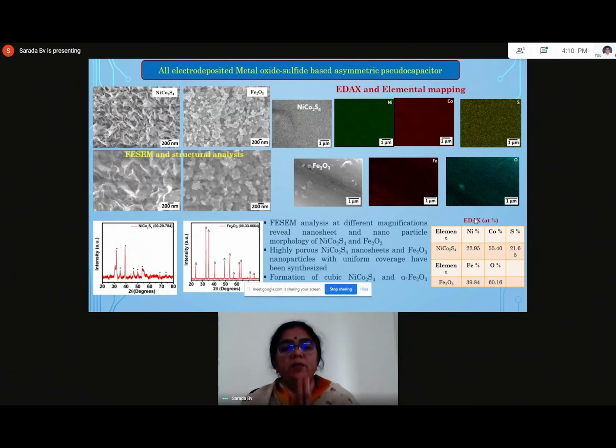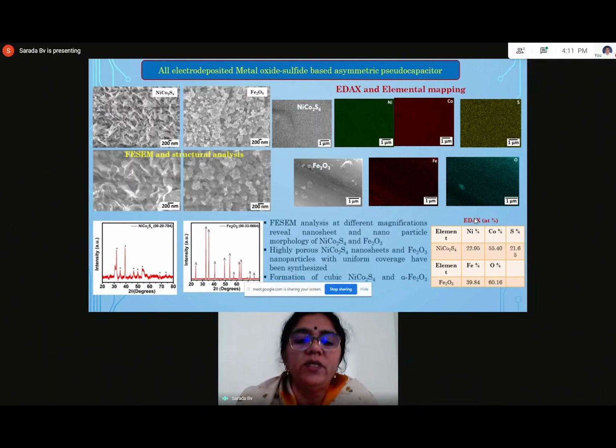And finally, previously what we have used is one carbon electrode and one metal oxide electrode and prepared an asymmetric capacitor. And now here, a step further she has gone and prepared an all-metal-based pseudocapacitor, both metal oxide or metal sulfide, metal composite based, by using nickel cobalt sulfide as one electrode and iron oxide as the other electrode in order to further improve the performance of this asymmetric pseudocapacitor. And you can see over here the very uniform distribution of each of the elements from the EDS results. And also the XRD results show that the